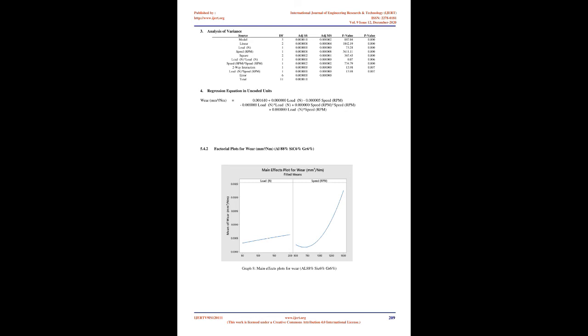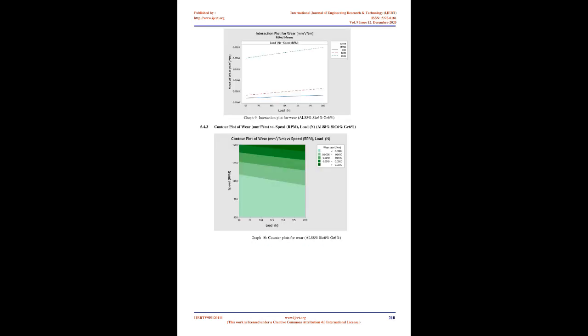Conclusion. 1. Aluminium alloy and its composite with SiC and graphite have been effectively fabricated by the stir casting method using two-step addition of particles in the melt. 2. Al6061, SiC and graphite composites showed uniform distribution of reinforcement particles in the base matrix material. 3. The wear resistance of Al6061 alloy increased after addition of SiC and graphite particles. The volumetric wear loss is affected by load and sliding speed. 4. Wear loss decreases with increase in percentage of SiC and graphite, i.e. addition of SiC 9 vol% and Gr 9 vol% to Al6061 decreases the specific wear rate.